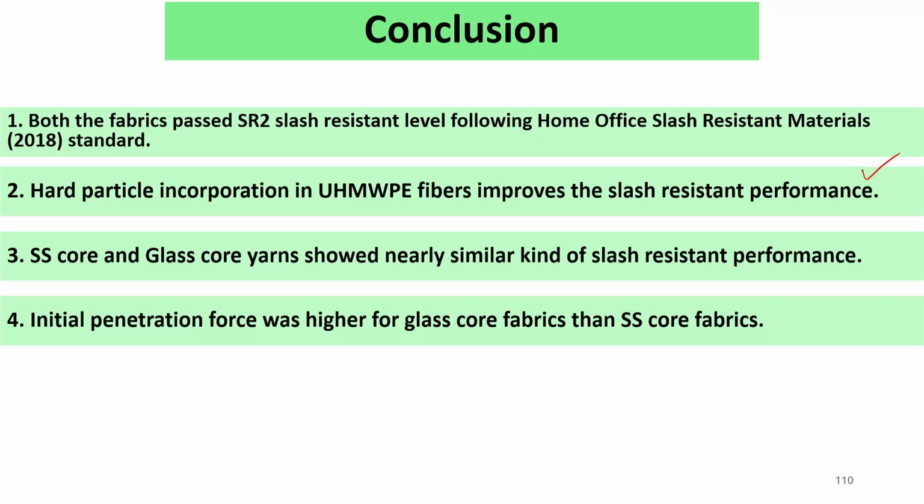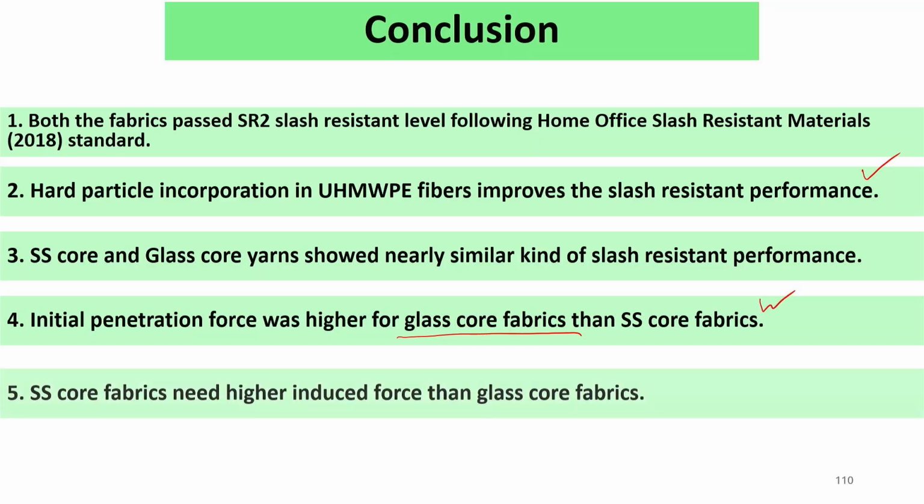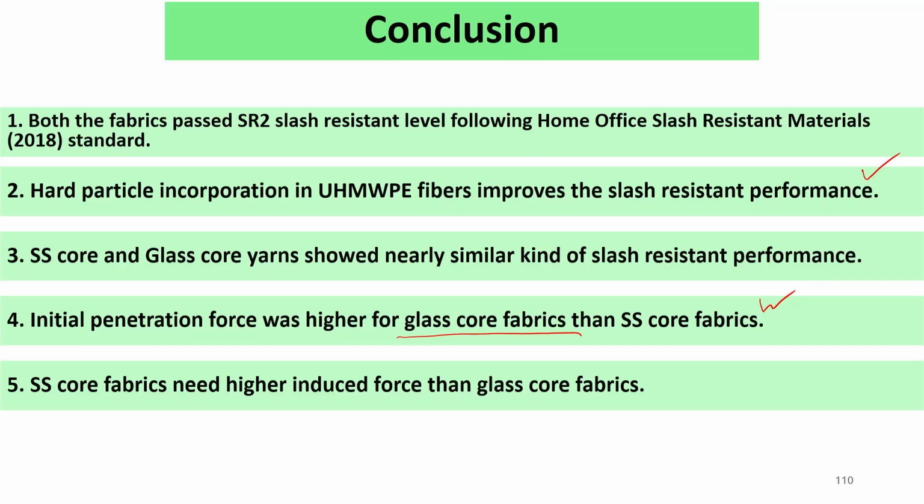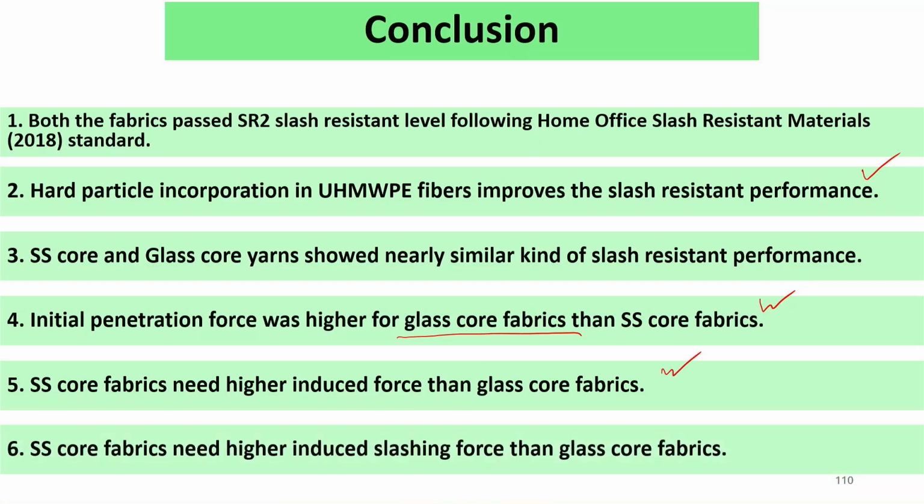Initial penetration force was higher for glass core fabrics than SS core fabrics. SS core fabrics need higher induced slashing force than glass core fabrics.